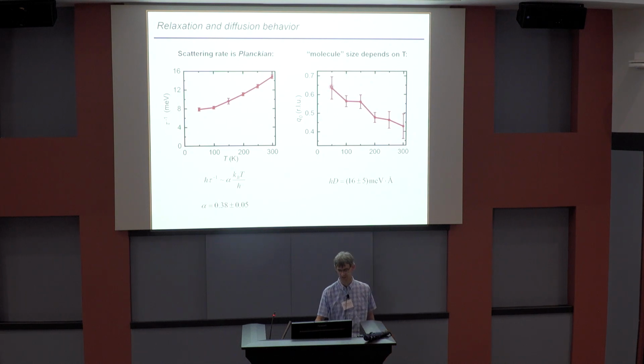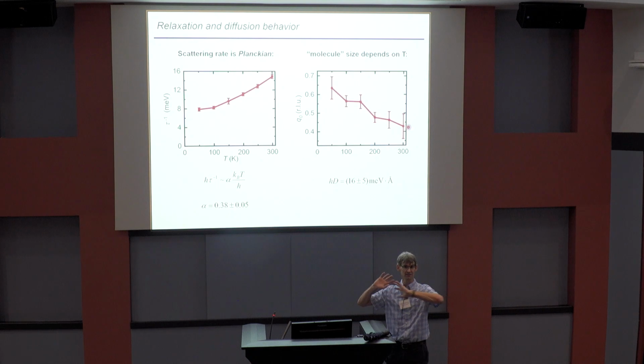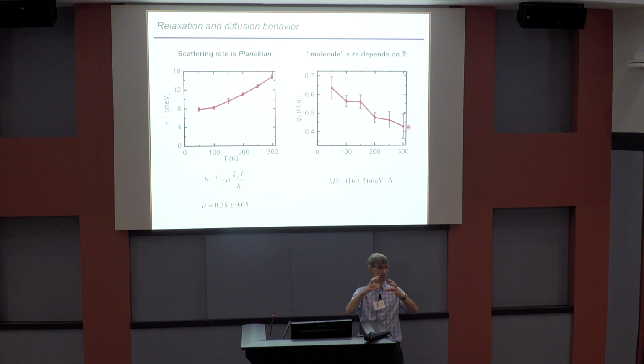And Q naught is temperature dependent. So this is in reciprocal lattice units, and you can see at low temperature it's about 0.65. At room temperature it's around 0.4. But what it means is that this strange metal is made out of fluctuating objects, but the size of those objects is temperature dependent. At high temperature, there are about 2 lattice parameters in size. And then as you go to lower temperature, they get smaller. So I don't know what that means, but that's what we see.